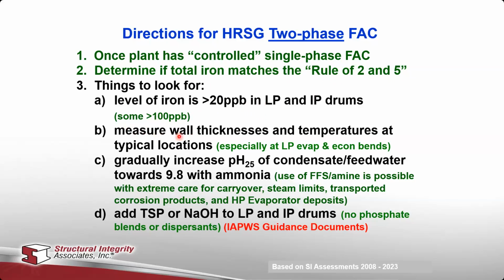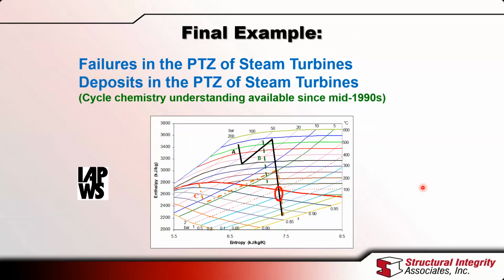You can measure the wall thickness of the tubes at the top of the LP evaporator and gradually increase the pH of the condensate and feed water towards 9.8. But as you're doing that, monitor the iron to make sure that the iron levels are decreasing. So these are the simple rules for single and two-phase FAC.